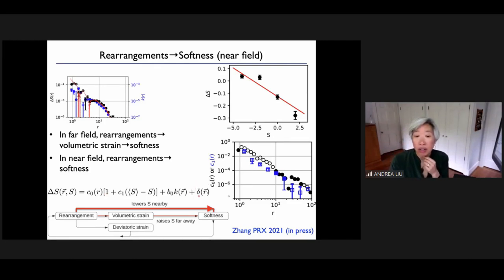And there's also, if we actually look at it, there's a distribution, and so there is a standard deviation. There is some noise on this, so we include that noise as well in this. All right, so a rearrangement then not only gives rise to this volumetric strain that raises the softness far away, but it actually, in this case, lowers the softness nearby, okay. Sorry, so it makes it less likely to rearrange nearby, more likely to reach further away.